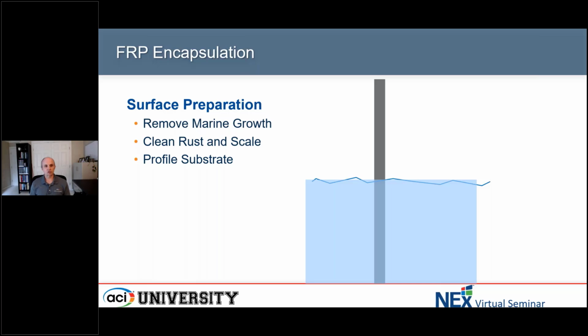So if we have this structure and it's partially underwater, partially above water, the first thing that we really need to do in order to repair a structure like that is we need to do some type of surface preparation. So this is no different than if we're repairing something above the water line. You've got to do proper surface prep to make sure that you remove any of the damaged, deteriorated concrete, remove surface rust and scale off of the structure, and hopefully give the underlying structure some surface profile so that we can bond new repair materials to it.